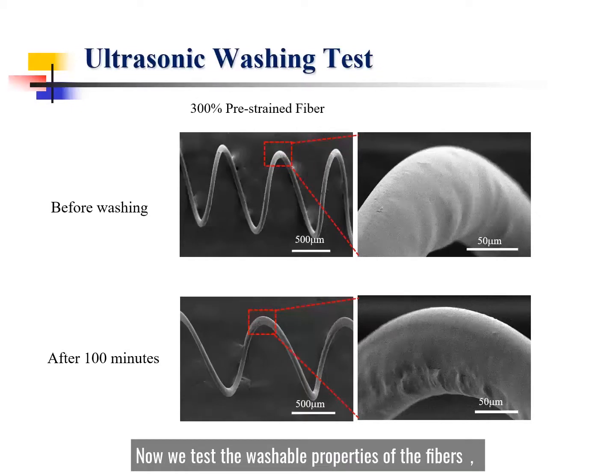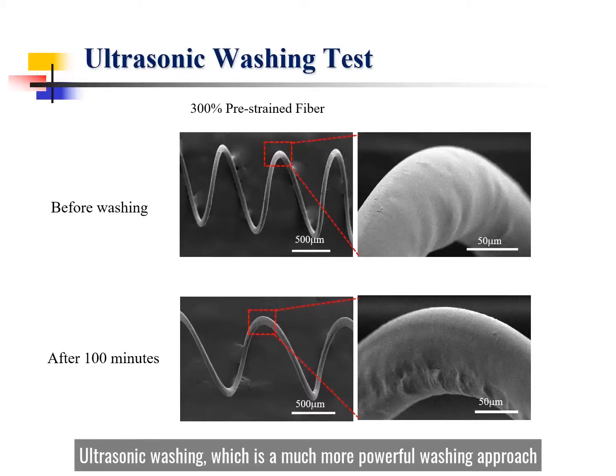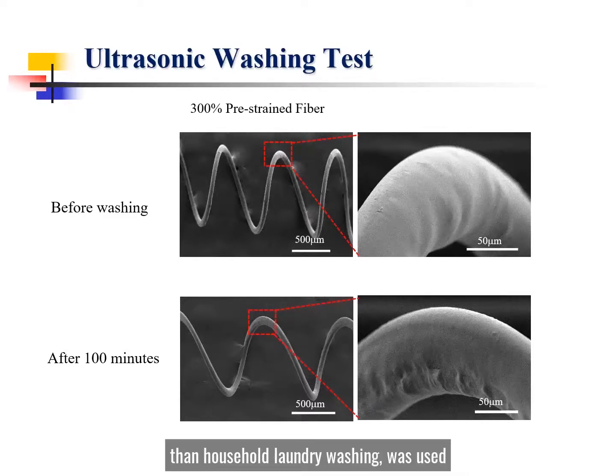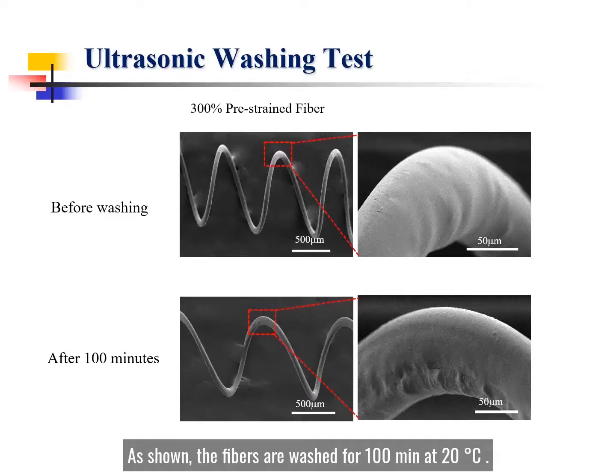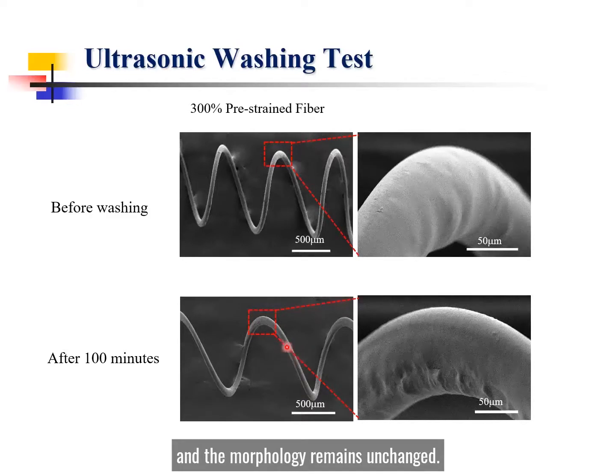Now, we test the washable property of the fibers. Ultrasonic washing, which is a much more powerful washing approach than household laundry washing, was used to remove solid particles from the object's surface. As shown, the fibers are washed for 100 minutes at 20 degrees Celsius. The fiber does not show severe mechanical damage, and the morphology remained unchanged.